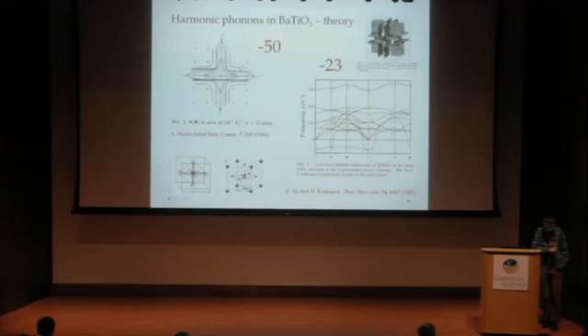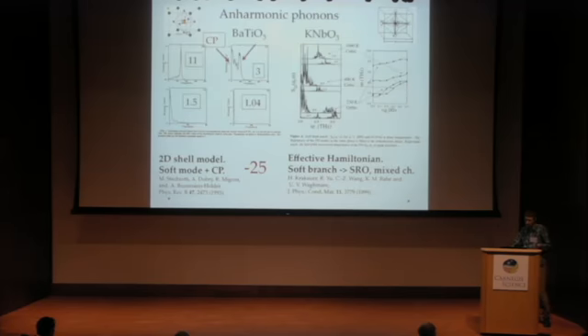by Henry Krakauer and coworkers in potassium niobate, showing that there is not just an unstable mode at the gamma point, but in many other directions in the reciprocal space, but not all. So this explains this anisotropy. So that's more or less understood since a long time.